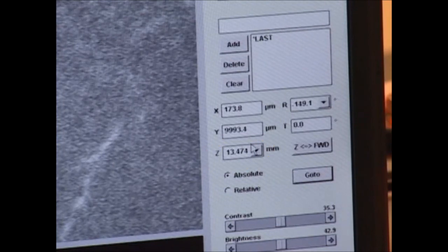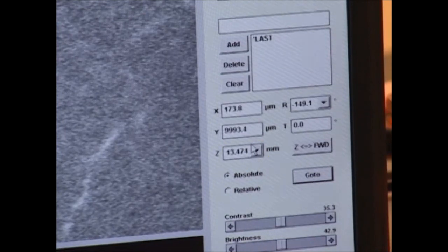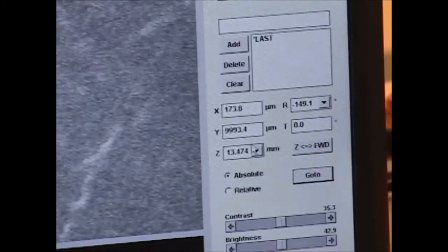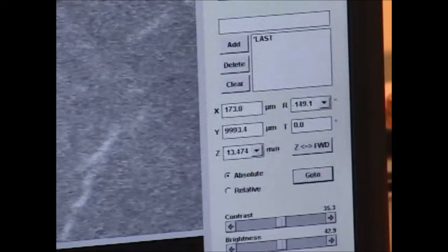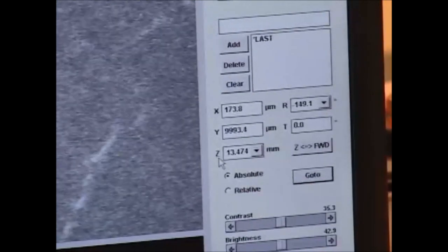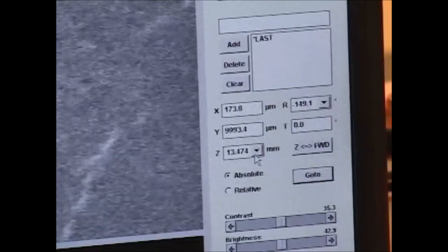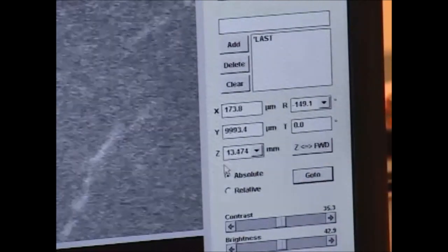Once I know how far it is to the sample and I've calibrated the stage height, I can reduce that height because the imaging is always going to be better at a lower working distance because there's less atmosphere for the beam to travel through. Ultimately, I want to do my imaging at about 5 millimeters working distance. As a safety measure, I'm going to reduce this to 10 millimeters first, recalibrate the stage height, and then move to 5 millimeters.